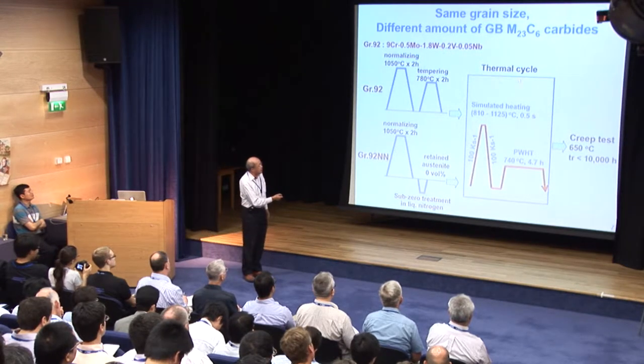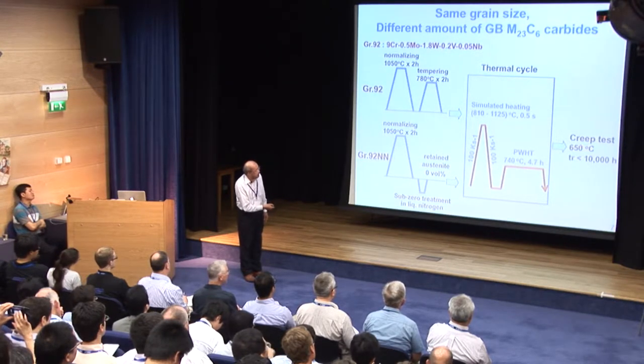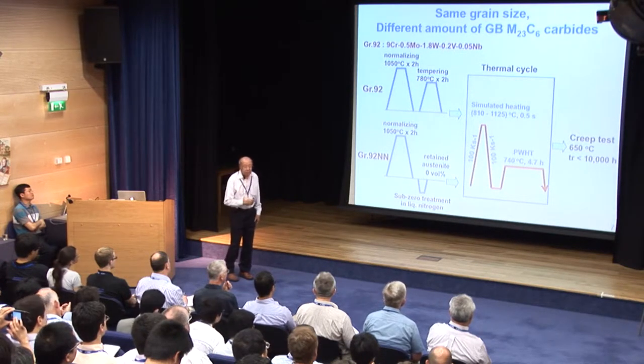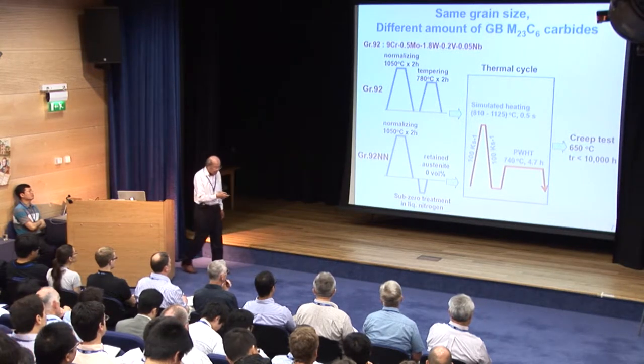After heat treatment, after thermal cycling, we carried out creep tests at 650 degrees Celsius for up to about 10,000 hours by using specimens having a 6 millimeter gauge diameter and 30 millimeter gauge length. Next, let me talk about the experimental results.